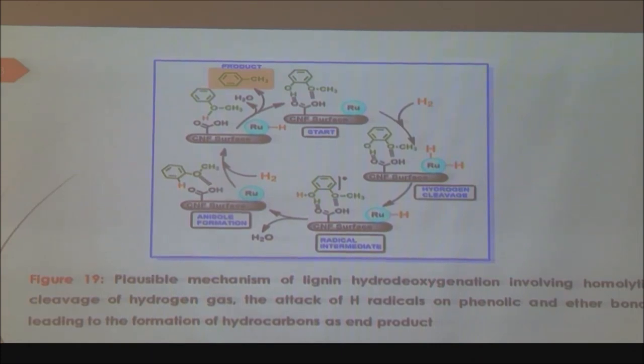So here again, we were unable to propose just one side of the mechanism. Again, we say that both mechanisms are probable, though the radical mechanism has the upper hand. If every facility is there, the reaction will definitely move through the involvement of radicals, and these radicals will finally be cleaved. This step we really need to understand right now, because we were able to get toluene with a very low activation energy, but what type of intermediate is involved in this step is still not clear to us.